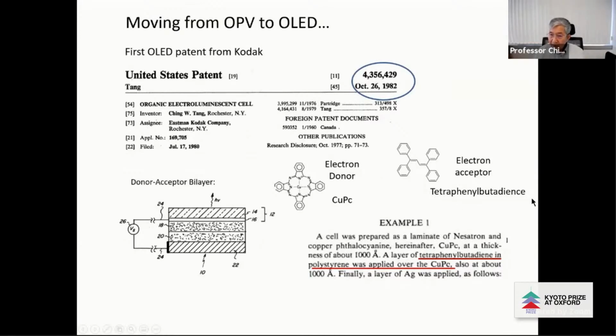I deposited an electron acceptor based on a very highly fluorescent material called tetraphenylbutadiene. This molecule was too small to be deposited by vapor deposition. It crystallized. So I mixed it with some polystyrene and spun it as a thin film. And this material emits blue light.